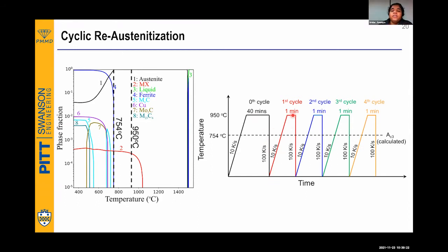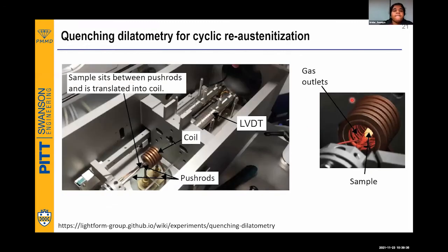And then we are doing different numbers of cycles. So for 1 minute holding at 950 degrees C, we have tried 4 cycles. So this is 0th, 1st, 2nd, 3rd, and 4th. And how are we going to do this? This is a not so new technique, but something which is known, called the quenching dilatometer.